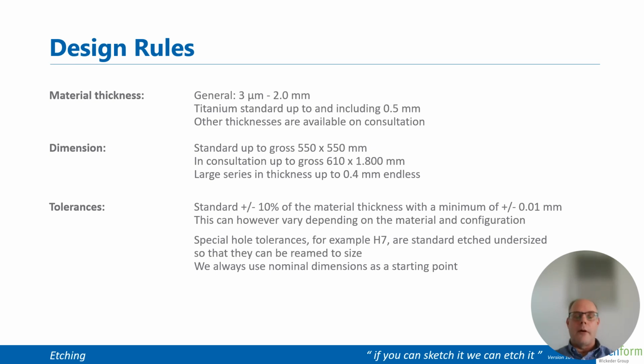If we look at how precise the technology is, as standard we can achieve plus or minus 10% of the material thickness, with a minimum of plus or minus 10 microns. However, this tolerance depends on the material and the configuration. Sometimes special tolerances are needed, for example H7 holes. In that case, a solution can be to etch them undersized and then ream them to size.